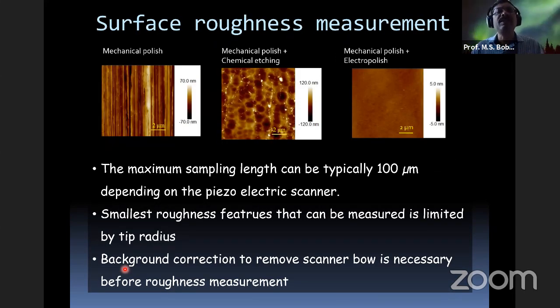So this is a typical AFM image of various surfaces. We always start with a mechanically polished surface because we understand that inherently. On the left-hand side, the whole lateral scan size is about 5 micron by 5 micron. The variation in the vertical direction, the roughness, is shown as a contour plot here. You can see that it is between plus and minus 70 nanometers. That is 140 nanometers, the typical variation in the height.